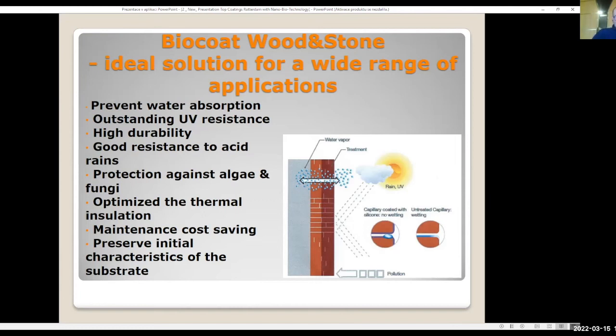For example, I have measured in one hotel in Dubai 43 degrees on the surface, and it was not the highlight of the day. It was around 9:30 a.m. With the direct shining of the sun, the temperature goes up to 50, for example, on the surface. And I switched off the air conditioning, and it was 33 degrees, although outside was 28 degrees.